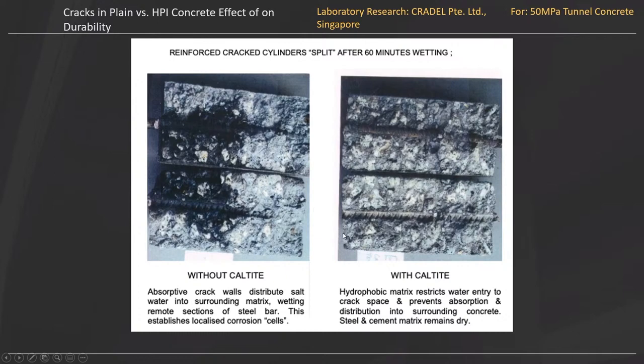If we break the samples open, split in half, you can see the sample without HPI is basically water has gone in through that crack up to the reinforcement. So if we have two layers of reinforcement, they are connected by an electrolyte. The sample on the right here, the sample with HPI, you can see inside it is absolutely dry. Water may have gone into the crack, but it won't go laterally, it won't move sideways into the concrete. There's no way that it can act as an electrolyte linking the anode to the cathode.